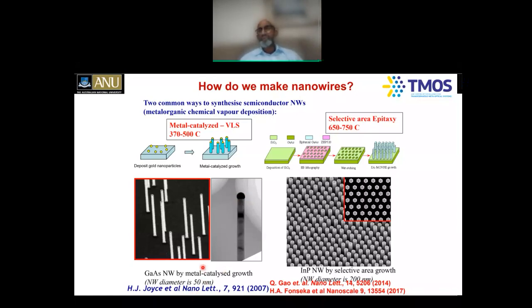Then we also work on selective epitaxy. In this case, we don't use any metals, because sometimes you don't want to use any metals. You deposit some silicon dioxide using plasma enhanced chemical vapor deposition, put on some photoresist, do electron beam lithography, and create patterns of holes. You transfer those patterns so that you have silicon dioxide everywhere, and in these holes indium phosphide is exposed, because we're using an indium phosphide substrate as an example.